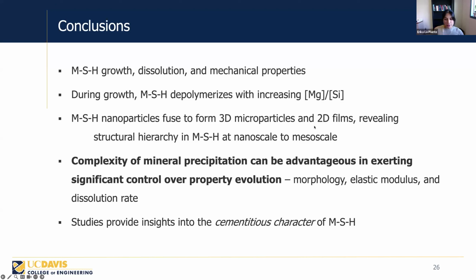There are two things here. We have evidence that shows MSH forms by crystallization by particle attachment. That means that we can affect the precipitation through either the first stage of the precipitation, the formation of the nanoparticles, or the aggregation of the nanoparticles themselves, which I think is a really interesting question. If you have an additive that controls the formation of the nanoparticles versus the aggregation of those nanoparticles, they could have very different effects on the final microstructure. Right, very interesting. And that is a very hot research topic right now.